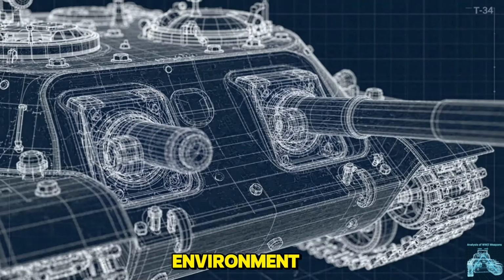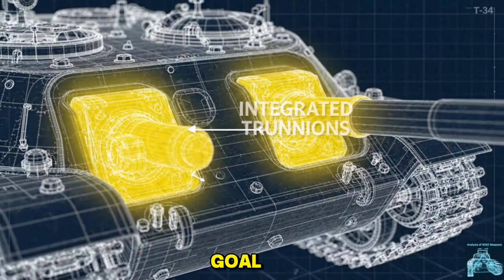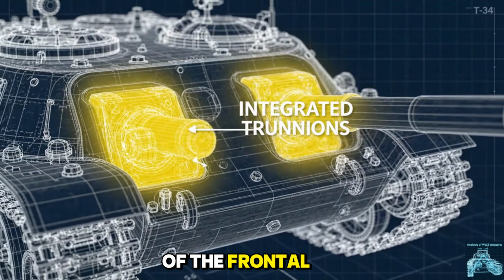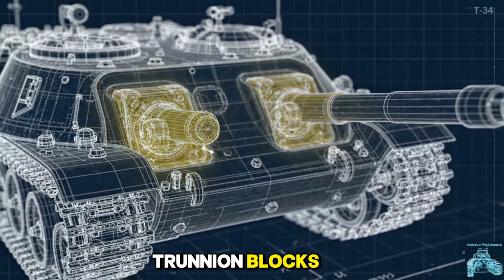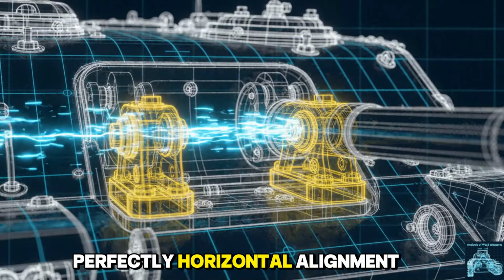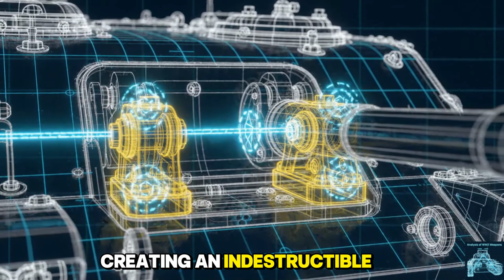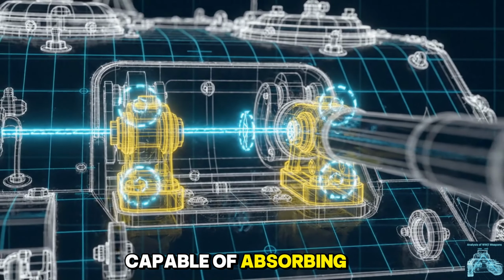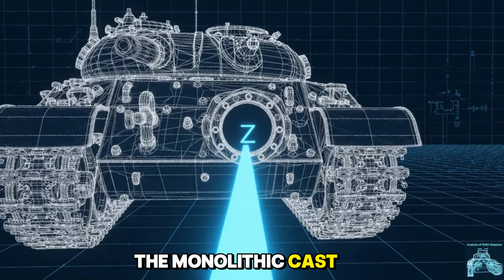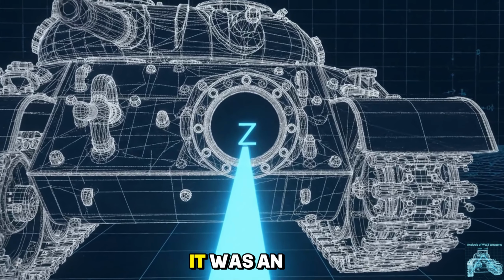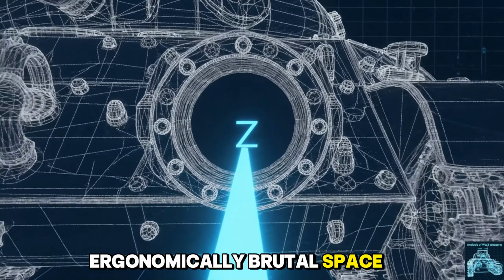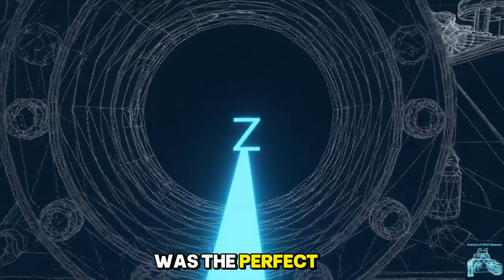Despite this chaotic environment, the casting succeeded in its primary goal. Molded directly into the thickest part of the frontal armor were the internal trunnion blocks. These blocks were precision drilled to perfectly horizontal alignment, creating an indestructible internal pivot point, capable of absorbing massive ballistic recoil. The monolithic cast steel bell was complete. It was an incredibly cramped, ergonomically brutal space, but mechanically, it was the perfect armored mount.